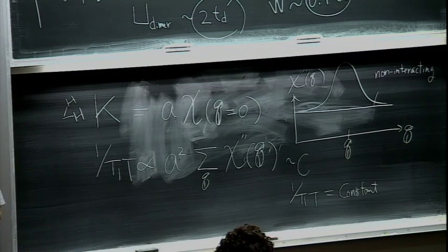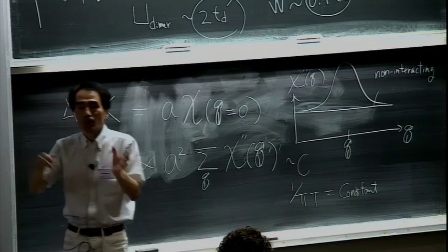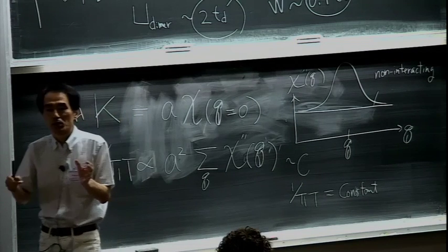As I said, the high temperature spin susceptibility is well reproduced by the triangular lattice Heisenberg model. This means above 10 Kelvin, the short-range order of 120 degrees is fluctuating. That is a guess. But below 10 Kelvin, something happens.